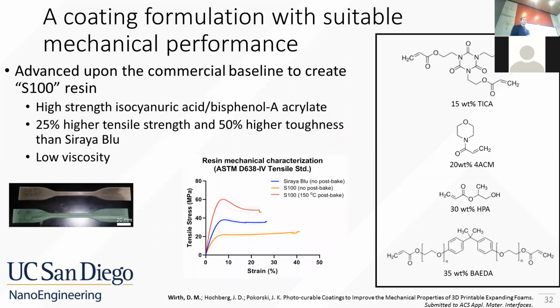There's already some commercial resins with relatively good mechanical properties. Siraya Blu is one of these resins, a urethane acrylate based oligomer. Unfortunately, the commercial resins tend to have very high viscosity, so you need a specialized paint sprayer, generally a high pressure, very large, bulky paint sprayer, to apply these resins. And this kind of contradicts with the overall goals here. The goal is to reduce the weight of the assemblers.